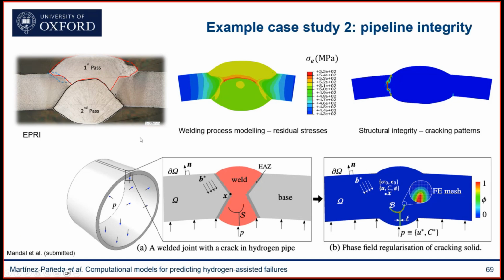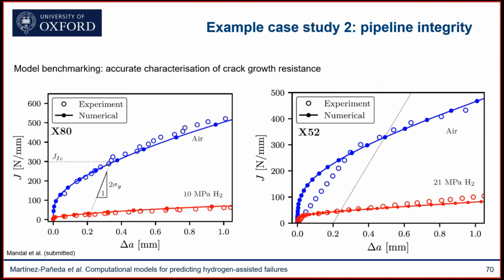And here we have a model that simulates two stages. First, we simulate the welding process, so we are able to predict what is the residual stress distribution. And there's a lot of nice work being done in the welding process community, where we have very sophisticated models for predicting the changes in phases and residual stresses during welding. And then we couple that with those models that I showed you before. So we're able to predict the structural integrity, those cracking patterns in the present parts.